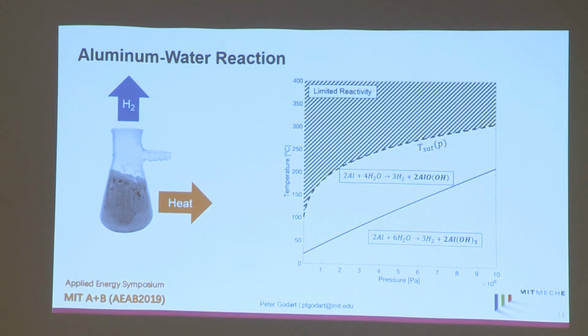And then finally, the amount of heat that's released in this reaction also changes depending where you are in this map. To give you an example, if we react this aluminum at atmospheric pressure at about the boiling point of water, 100 C, we find that we get 11 kilowatt hours of heat per liter of aluminum that we react. And then the lower heating value of the hydrogen that's evolved in this reaction is about 12 kilowatt hours per liter worth of aluminum.